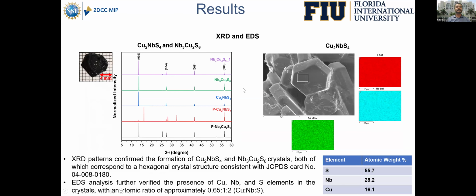So we are trying to synthesize. We have tried to synthesize these two crystals, and the XRD pattern confirms the formation of a hexagonal crystal structure. And through the EDS, the sulfur, niobium, and copper are uniformly distributed all over the surface. And the atomic percentage of this Cu2NbS4 gives approximately a 0.65 ratio to 1:2 for copper niobium sulfide. So we can say that it's copper doped niobium sulfide.